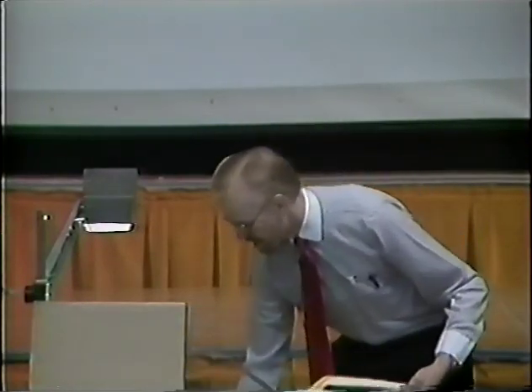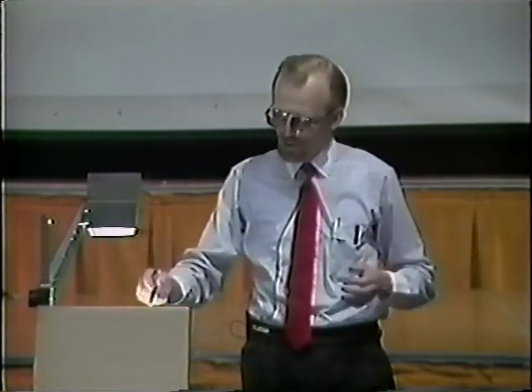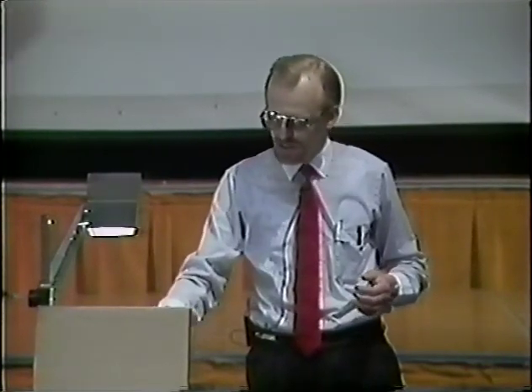On the next curve here, I have shown the results for multiple occupancy of a given vacancy. If you have a vacancy, then in an FCC metal, you have 6 octahedral sites around the vacancy. And the dots here are the results from the calculation, where we have tried to put 6 hydrogen in a certain vacancy. What turns out to be is that all the trap strengths here are now measured relative to that for only a single hydrogen in a vacancy.